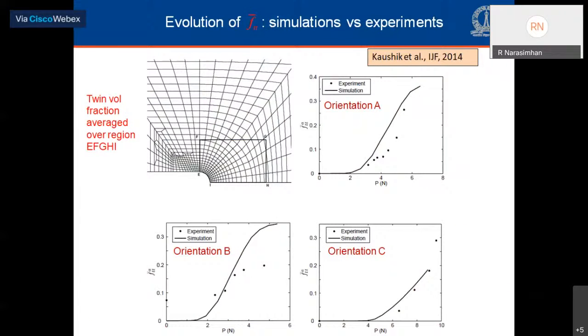We also quantified the average twin volume fraction by considering a rectangular domain in the finite element model, which is marked out here as EFGHI, and calculated the average twin area fraction, plotted it against load, and compared with the experimental data. We see a reasonably good agreement for orientation A and C, whereas in orientation B, there are some differences. These differences are attributed to the fact that in the experiments, there were some polishing twins, which, as I said, impeded subsequent twin development, which is not captured in the simulations.